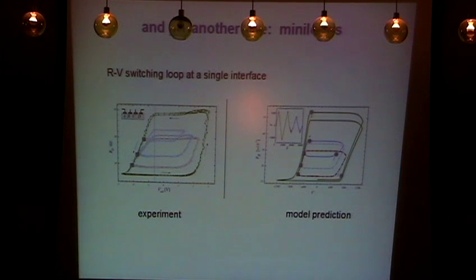Different systems will, a key point there is how you relate the vacancy concentration to the resistivity. And that is very strongly material dependent. For instance, in this case, manganites or YBCO, these are rather metallic systems. So the main effect of putting vacancies there is just to break the PD chains that produce the conductance. So having more vacancies increases the resistance.